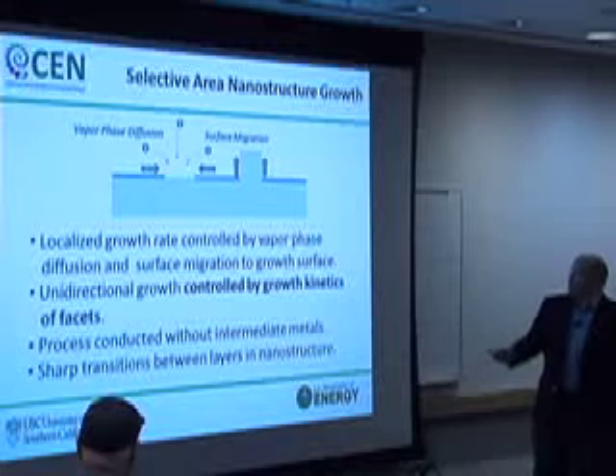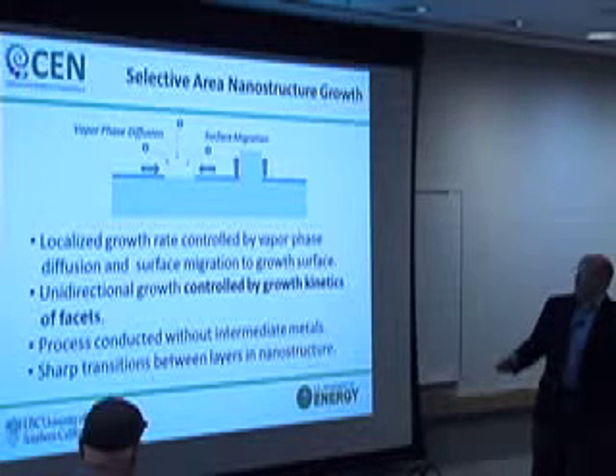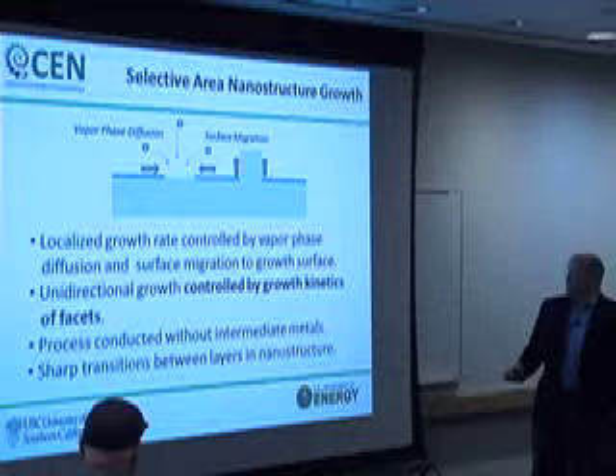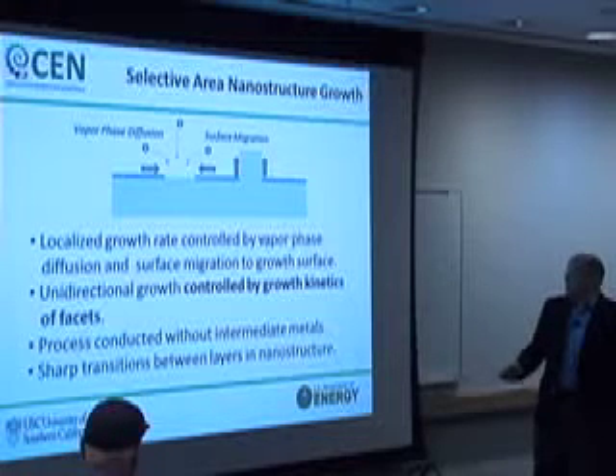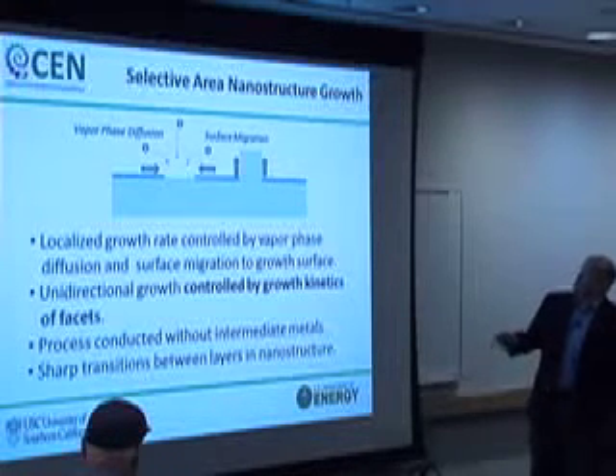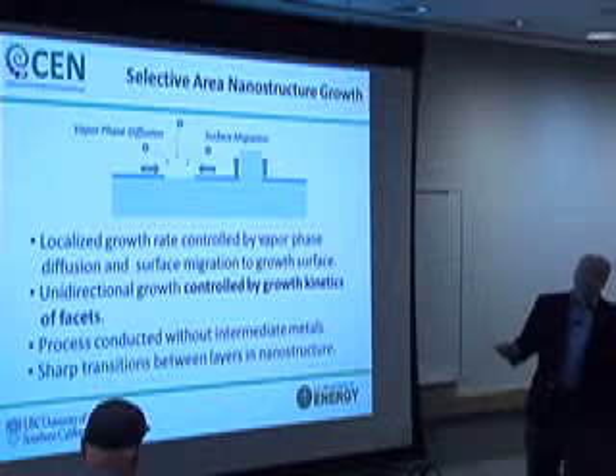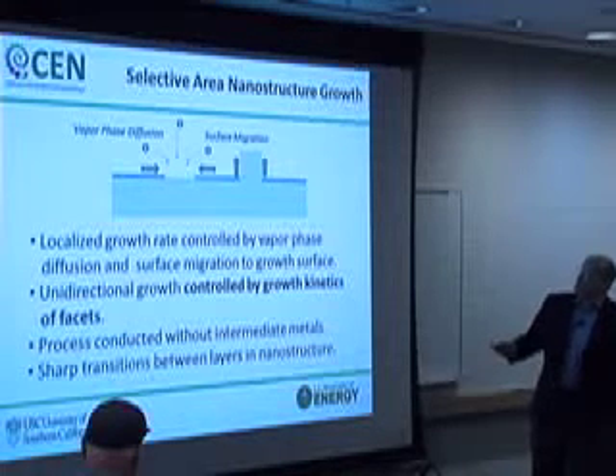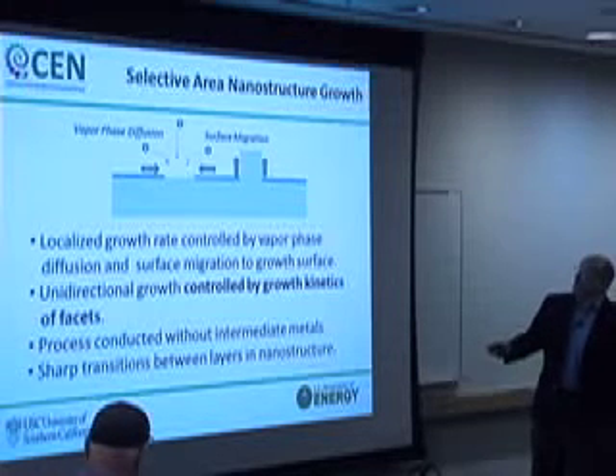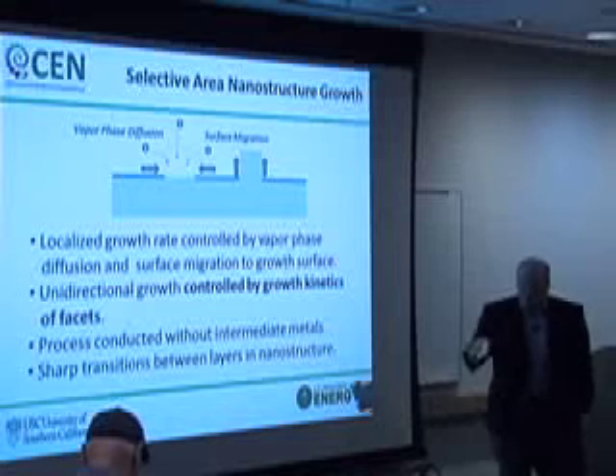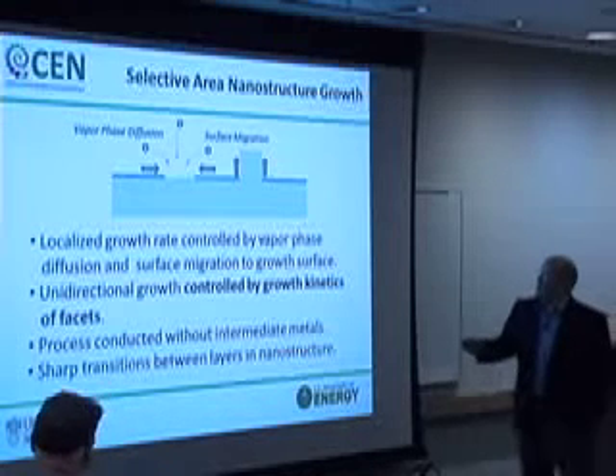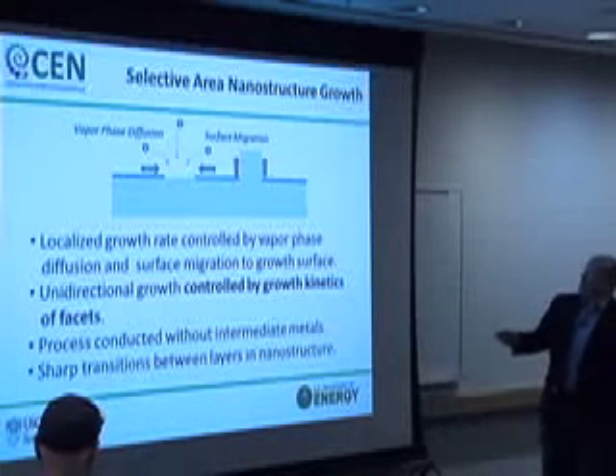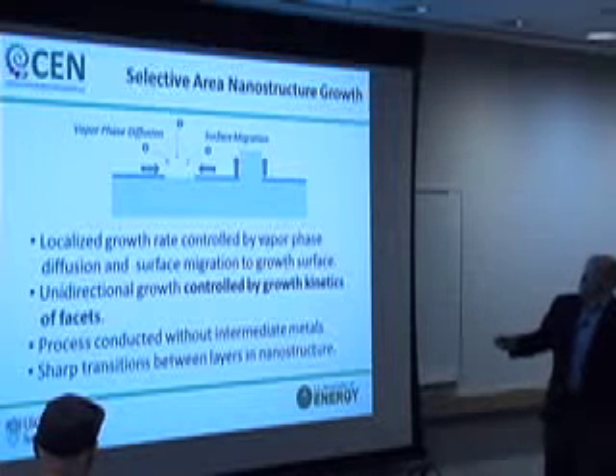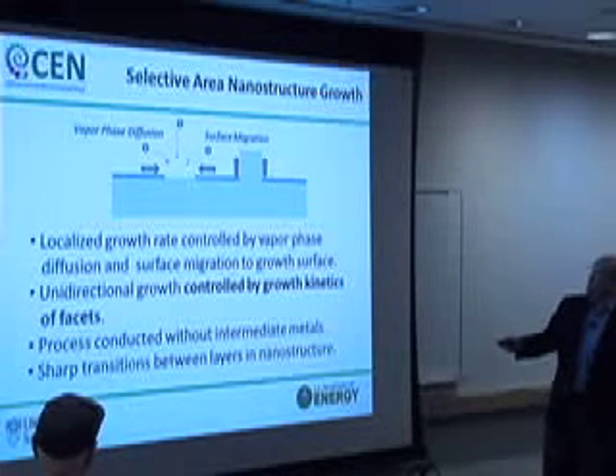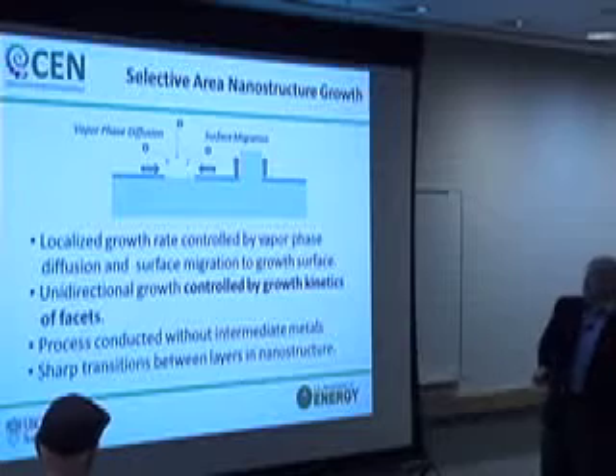And so it's necessary to control the growth kinetics of the various facets in order to achieve that. Now, this is to be contrasted with vapor liquid solid growth, in which people have done an extensive amount of work by using, say, a small ball of gold or some other intermediate metal that absorbs the vapor phase reagents and then redeposits the material underneath as the ball propagates upward.